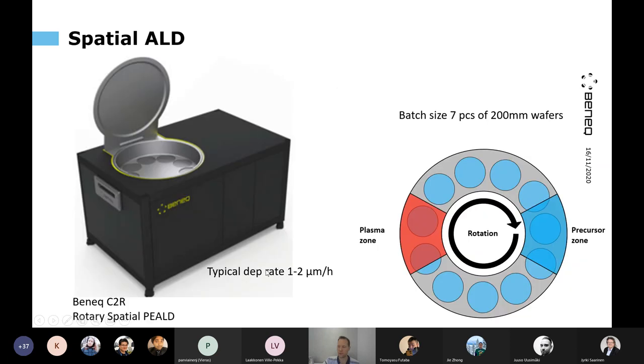And the other way of doing ALD is what is called spatial ALD. So in this example, we have two of those materials that we need to make the deposition. So a metal precursor here, and then the other co-reactant or the other material, in this case, not using water, but instead oxygen plasma. So anyway, here is the oxygen plasma zone then. And these are constantly on, not pulsed, but they are on all the time.